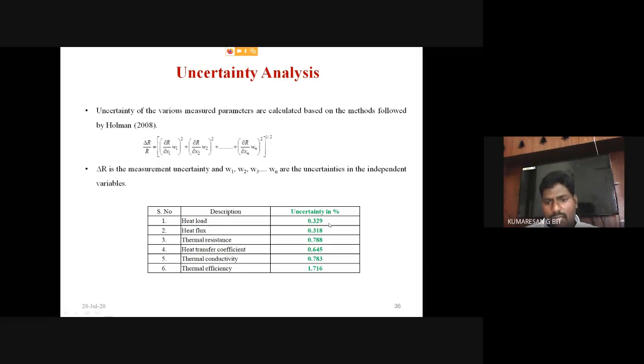For the heat load calculation, I attained nearly 0.329, heat flux 0.318, for the thermal resistance calculation 0.788, for the heat transfer coefficient 0.645, thermal conductivity measurement 0.783, and for the thermal efficiency calculation it is somewhat high, about 1.716, because to measure the thermal efficiency value I used an orifice flow meter, which has a very low accuracy of plus or minus 3%. That's why the uncertainty in the thermal efficiency is somewhat high compared with the other parameters.